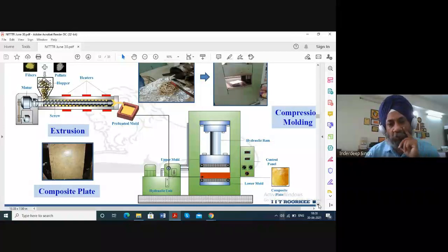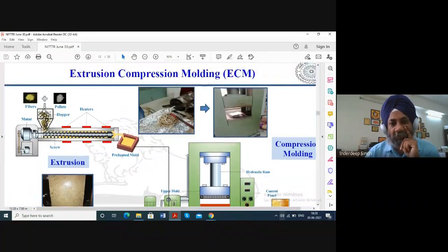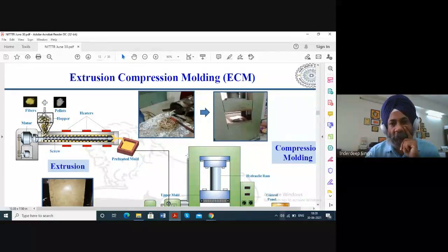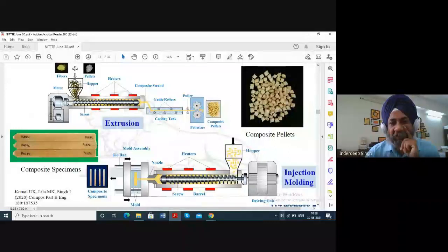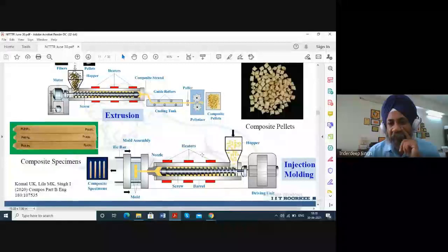So in case of extrusion, if I go to the previous slide, you can see that we were pelletizing the samples. You see here, this is an additional setup that we have designed and developed for pelletizing. So we are making the pellets which were used as raw material, but in the next process we are not pelletizing.